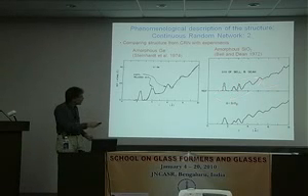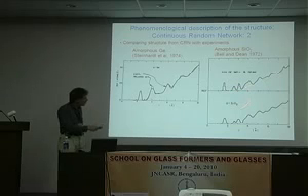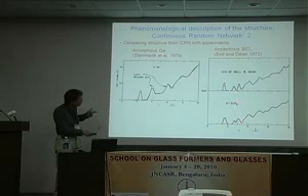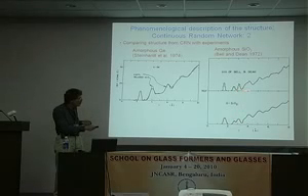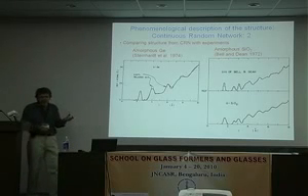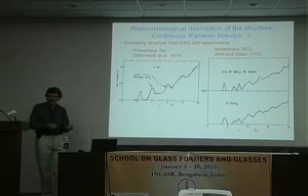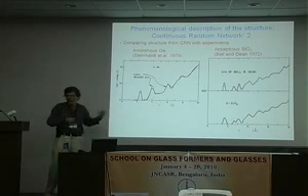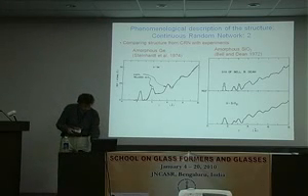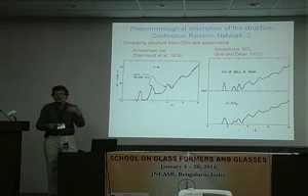And they got out this radial distribution function. And if you measure it, then you get something like this. And okay, you see that there are slight differences, but in an approximate way, more or less the location of the peak and the relative height of the peak, for example, that this here is smaller than this, you indeed find it. And if you imagine how primitive this model is, the success is not too bad. And these days, nobody's really doing this anymore, but as a concept, it's still quite nice. No, this is zero temperature if you want.